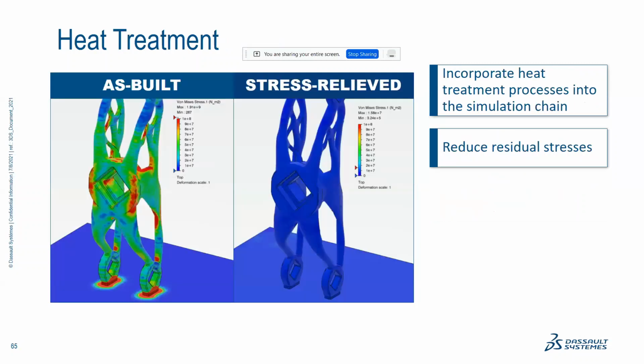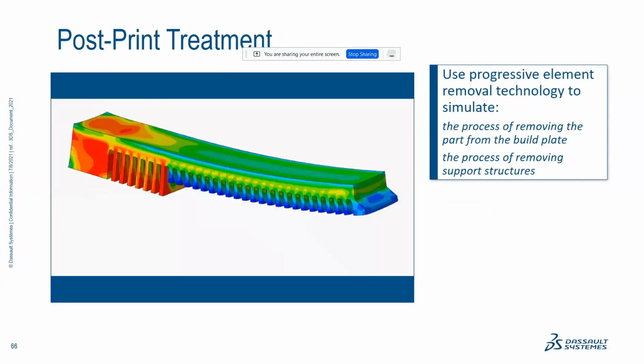And once the part is virtually printed, the stress solution along with the temperature solution is going to be at a steady state. We can eventually go in for some sort of annealing or stress relieving process to reduce the residual stresses virtually. And then as I mentioned earlier, we can even do post-print treatment by removing certain support structures which have been tied in initially itself.